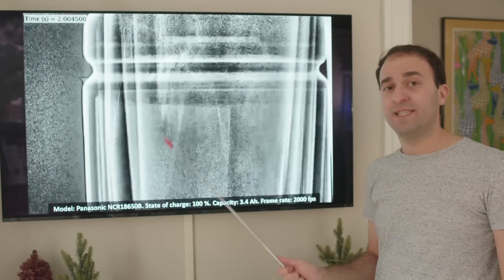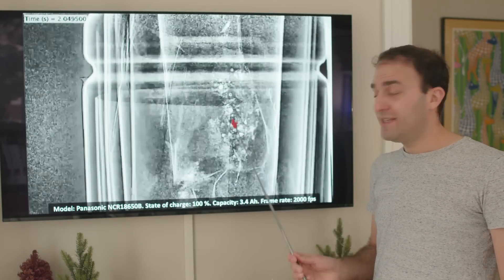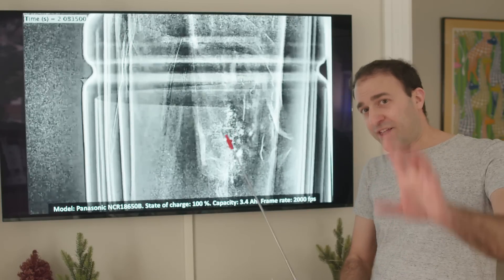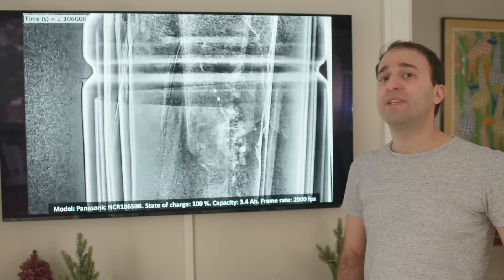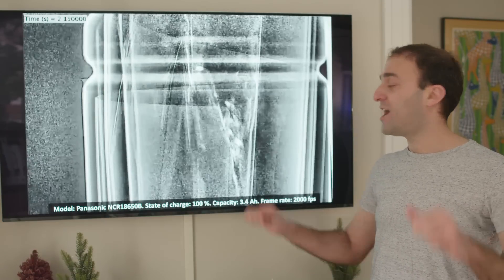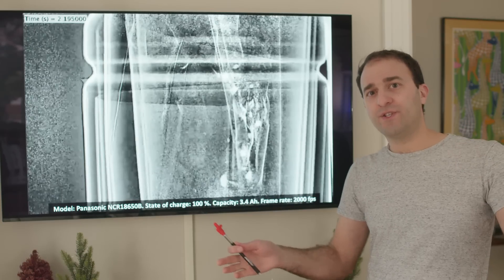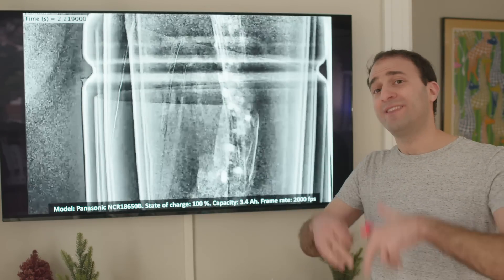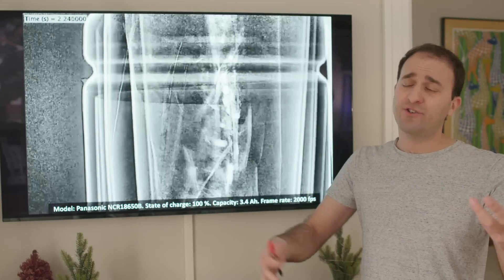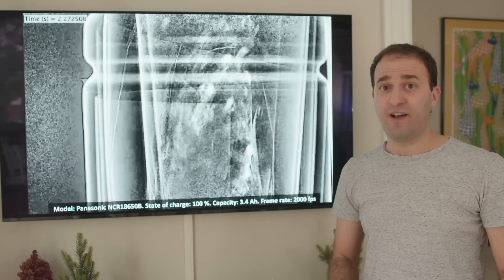This is the aftermath — complete devastation. These white globs are molten copper. Copper melts at 1,085 degrees Celsius, so inside this battery you've got temperatures about as hot as a steel forge. Now, if one cell thermally runs away, it can heat the surrounding cells to the point that they do too, and you get a chain reaction. Pretty soon you've got a massive battery fire.